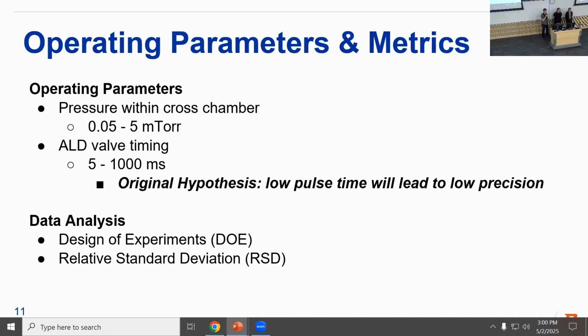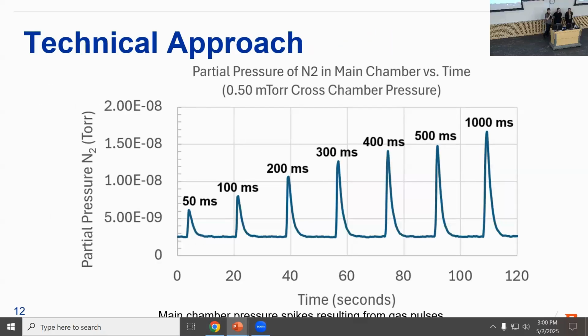This gives us a way to look at the precision and consistency of our gas dosage compared to the various parameter levels. So here's what our data looks like when it pops out. We have the various pressure spikes resulting from our increasing pulse times. Once we get this data, we would integrate under these pressure spikes to get the total change in pressure. And then just using the ideal gas law, we would relate that change in pressure to change in moles and the number of molecules emitted. We did 5 trials for each pulse time of sub 50 milliseconds, and then 3 trials for the 50 to 1,000 milliseconds to get a good standard deviation measurement.